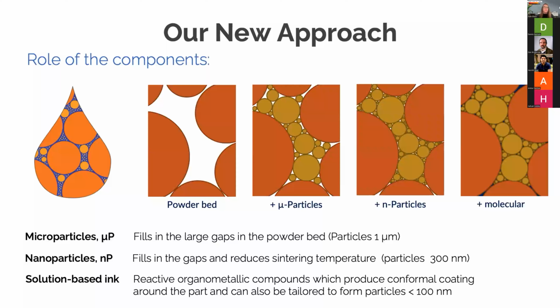So the process which we developed at Liverpool uses binders that don't just see the binder as a binder. It doesn't just hold polymers. In fact, in many of our applications, it has no polymers at all. In fact, we have a jetting solution that has functional fluid, and this acts as a binder and simultaneously as an infiltrator. So the binders are reactive solutions, and hopefully you see here in this schematic how they all build up and what role they play in that system.